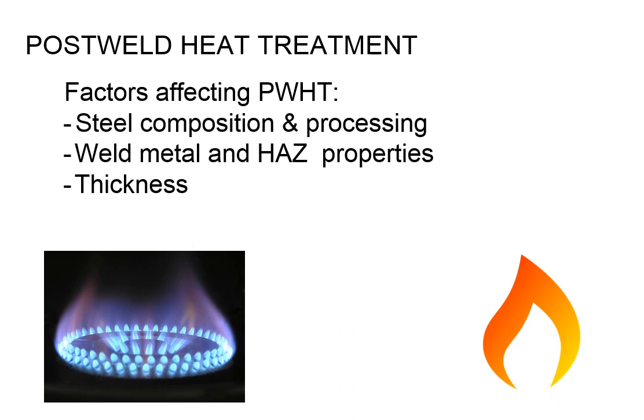You've got to look at the weld metal and the HAZ properties you're looking for. These need to be taken into account when you're looking at post-weld heat treatment. And the thickness of the material also comes into play. Because if you put something in the oven that's 10 inches thick and you just cook the outside, you post-weld heat treat the outside and you don't get the inside, well, then you kind of defeated the purpose, right? So these are the things, to me, I'm trying to boil down pages upon pages of post-weld heat treatment into 3 lines. And to me, it is steel composition and the processes that have been done to get it to those mechanical and physical properties that you're looking for, the processing, the weld metal and HAZ properties, and the thickness of the material.